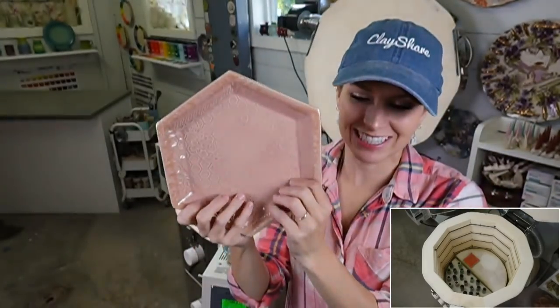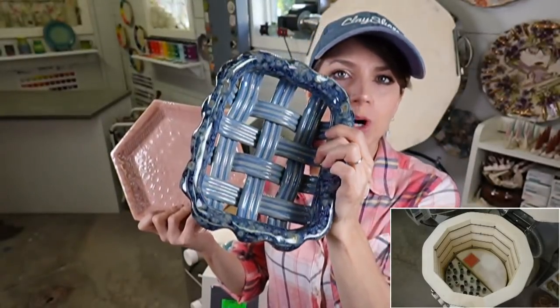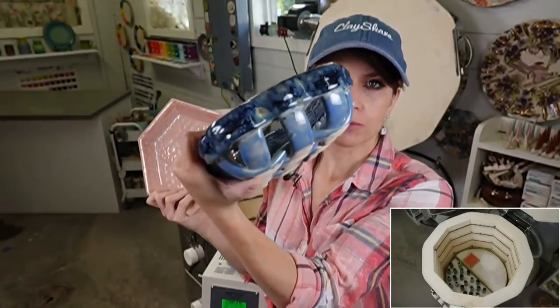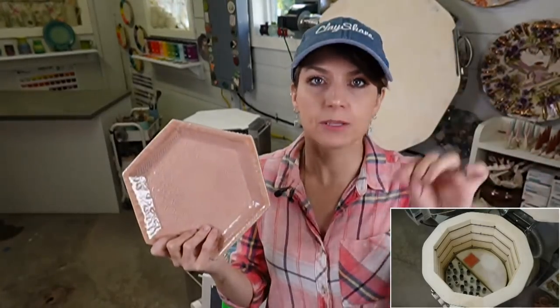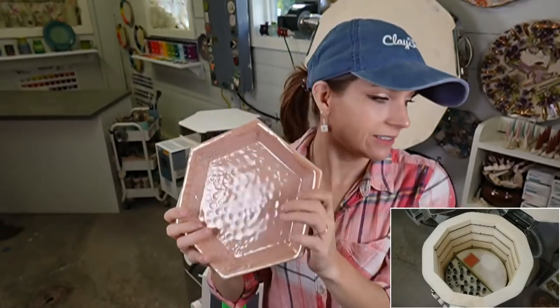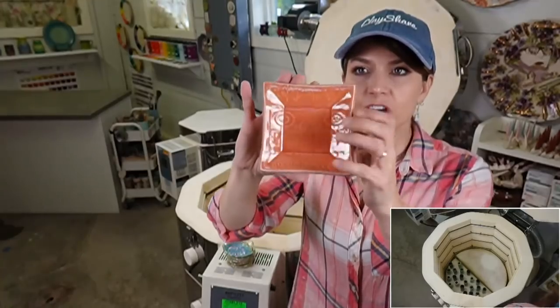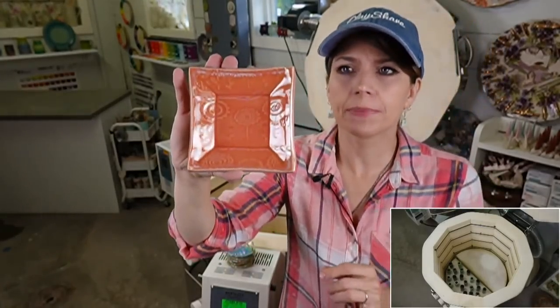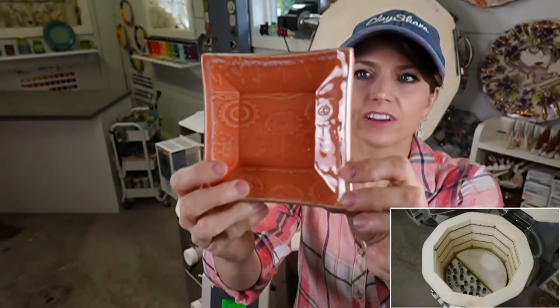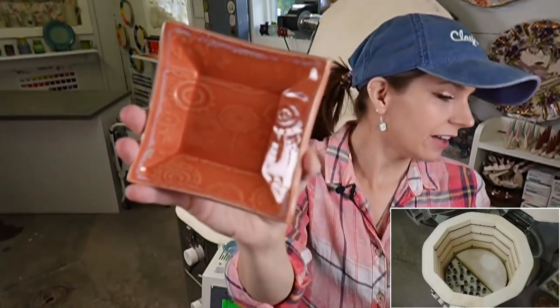The colors on the basket were Mayco blue opal and Mayco night moth. Blue opal on the entire thing two coats, then night moth over on the rim two coats. The key is you have to put the night moth on top of the blue opal to get that beautiful starry-night blue effect. Then I did Amaco poppy — I think three coats — with Mayco light flux, two coats, very subtle on the rim.